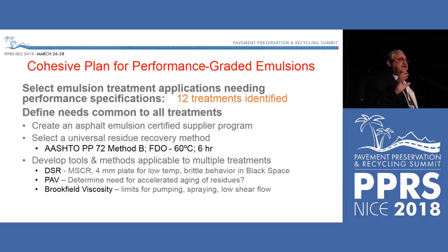First, to do this new system, we have to start with a plan that anticipates how we're going to develop a system that includes all those 12 different applications. We have to have one single common residue recovery method. And it can't be the distillation method of the past at the really high temperatures. We want a recovery method that is at a temperature that is similar to what we have on the pavement. And in fact, the Europeans are far ahead of us with the 50-degree forced draft oven, and we're using 60 degrees instead of 50 degrees.